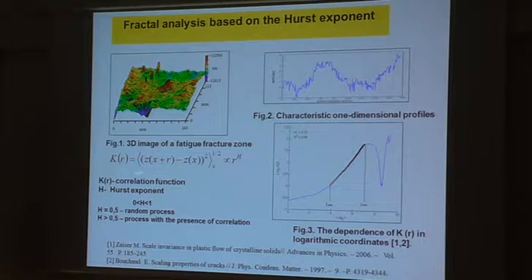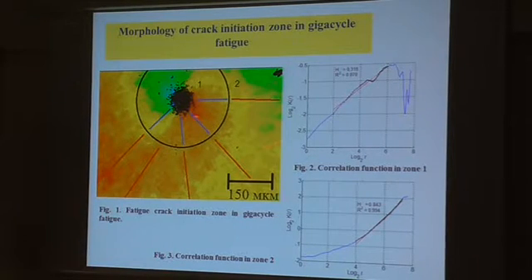And using the well-known technique concerning correlation function estimation, we have used results of precise morphology after interferometer profiler NewView. We investigate characteristic areas in terms of correlation of defect-induced roughness for FGA area and the area of crack propagation. And you could find for different areas, we have different Hurst exponent. That exactly, but there is scaling according to defect-induced structure, which is different for FGA area and the area of crack propagation.